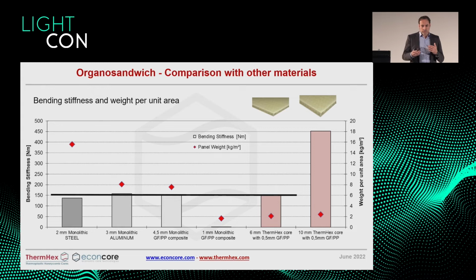And cost-wise, these glass fiber composite skins, as well as our polypropylene honeycomb core, you can say about €4 per kilogram is a good price for a large volume. And if you add €4 per kilogram to this 2 kilograms per square meter, then you have about €8 per square meter where you can get a sandwich panel.